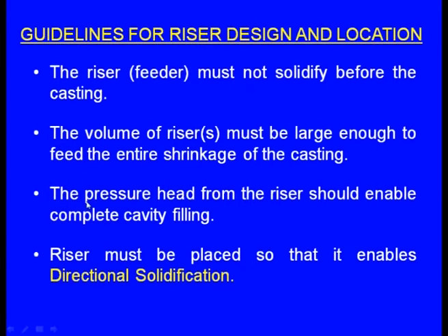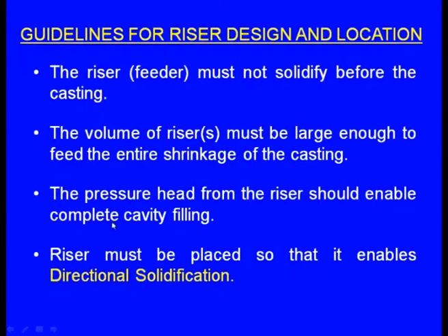The third guideline is that the pressure head from the riser should enable complete cavity filling. No part of the cavity of the mould should be left out without the molten metal. Next, the riser must be placed so that it enables directional solidification. The position of the riser must be such that there will be directional solidification.